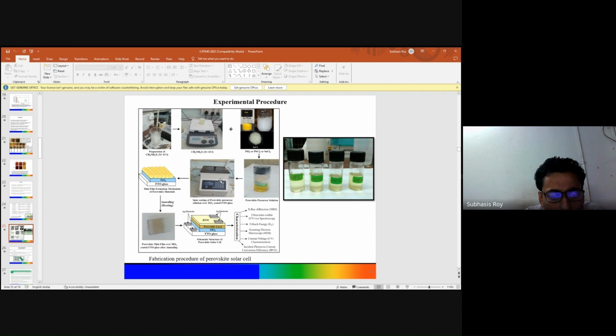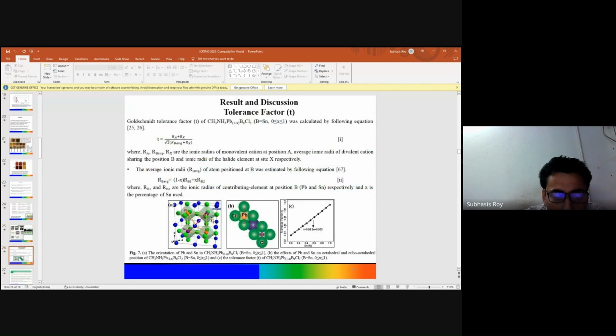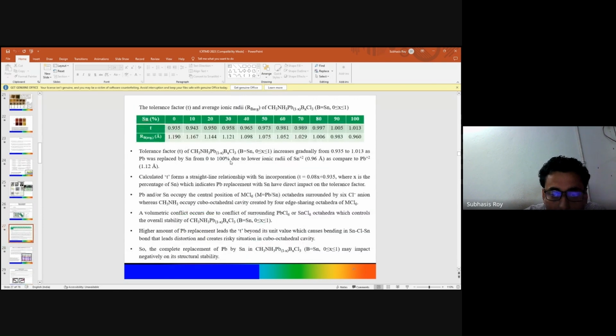And after spin coating, these are the fabrication techniques of the solar cell fabrication process. I am not describing these steps. After fabrication, we check the stability and tolerance factor by XRD, and you see that after changing the percentage of the Sn, a certain percentage is giving the best tolerance factor, around 20% Sn. We are getting the most stable tolerance factors.